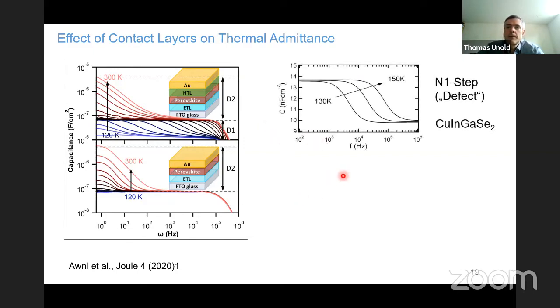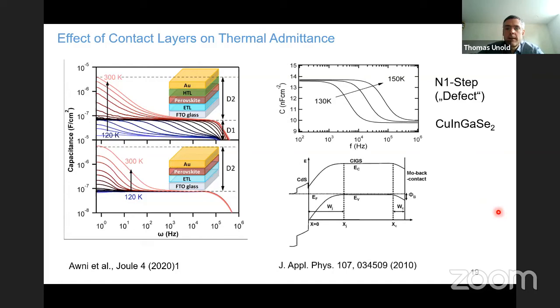And that reminded me of a discussion we had 10 years ago on CIGS. There, people usually recorded at low temperatures the capacitance step versus frequency. It was called the N1 step and interpreted as interface defects, and there were big discussions about that. At that point, through a detailed study where we also varied the contact layers and so on, we could show that this step is actually not due to an interface defect, but to a back contact barrier that can produce this artificial capacitance step in your capacitance response. So this is also something that can happen.